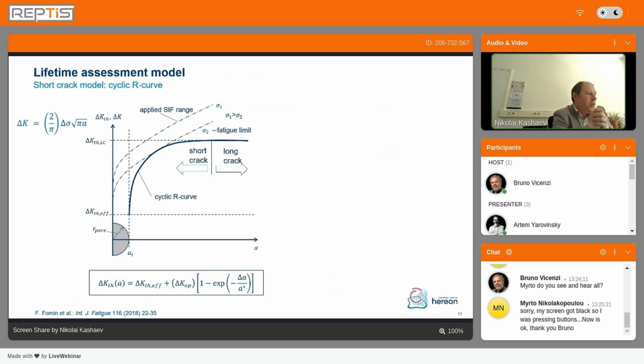For example, using this analytical equation where we need the data, for example, with regard to crack growth and the parameter A star, which we need. And if we have the crack in our component, we can use fracture mechanics-based approaches to calculate the stress intensity factor from the crack dependent on its length. For example, this is the analytical approach.